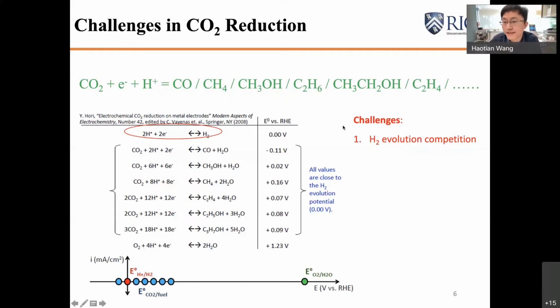So one of the biggest challenges is the competition from the hydrogen evolution reaction. Most catalysts, if you test their CO2 reduction performance, tend to dump electrons to water instead of CO2, because CO2 is a relatively stable molecule. There is also low selectivity, not only because we dump electrons to hydrogen, but also because all the reaction pathways towards different products have very close thermodynamic potentials. So the electrons can feel free to go to different types of products, and that results in low selectivity towards a single product.